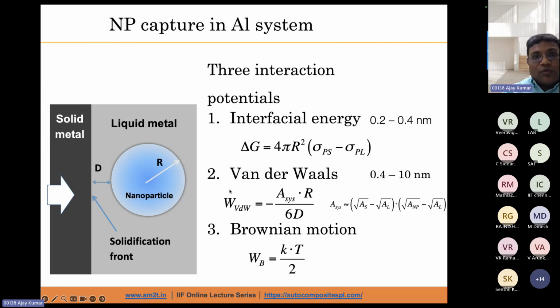And then we can also use the nanoparticles. So when we use different types of particles, we embed the particles in the matrix, and we face a lot of challenges during the mixing. So these particles generally agglomerate during the mixing. So we have to carefully understand how we can mix these particles, because they are going to have a very high energy interface surface area. So we have to control the distribution carefully, so that we can get the uniform dispersion when we use the micro size particles or nano size particles.